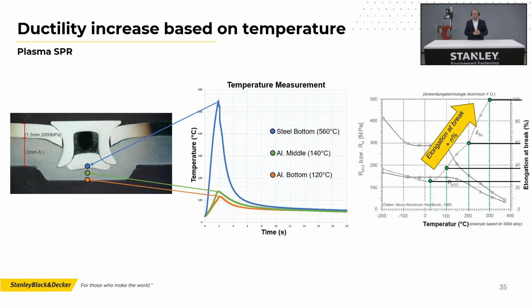On the right side, you can see a graph that's an example for 5,000 alloys. You increase the elongation at break values, which means you increase the ductility, which means you have an easier life in joining these brittle materials, and you don't get cracks with that. Okay, but again, we are shooting from the top, and heat is traveling through to the bottom.